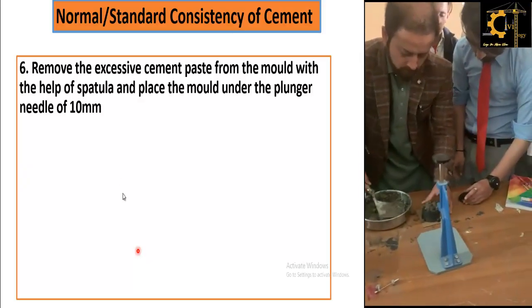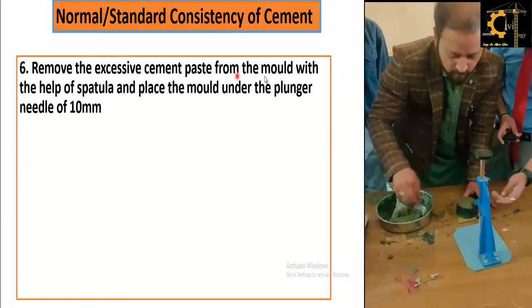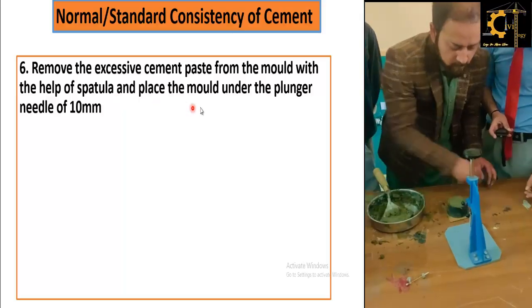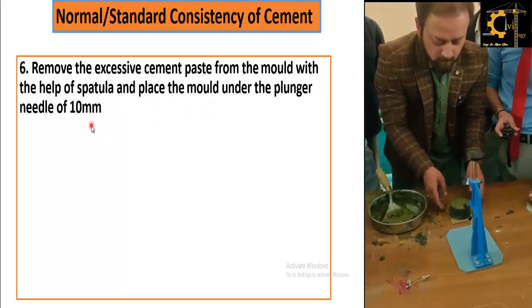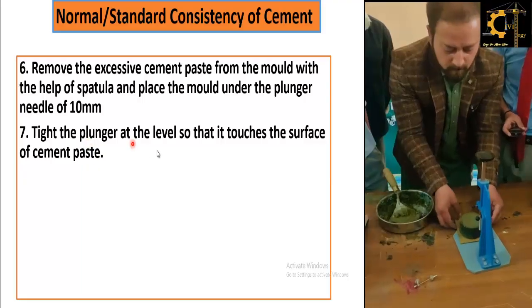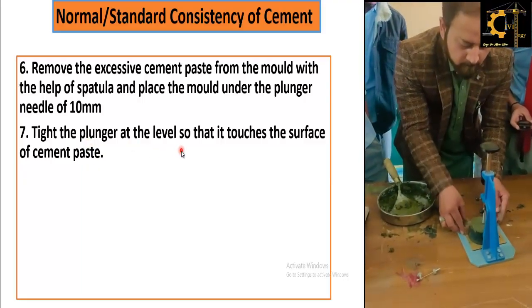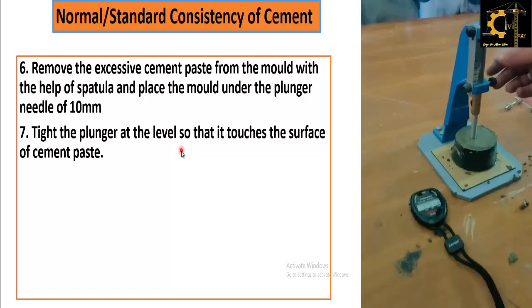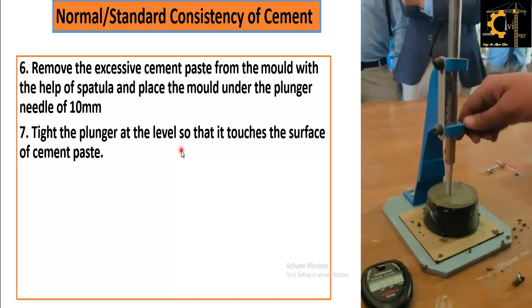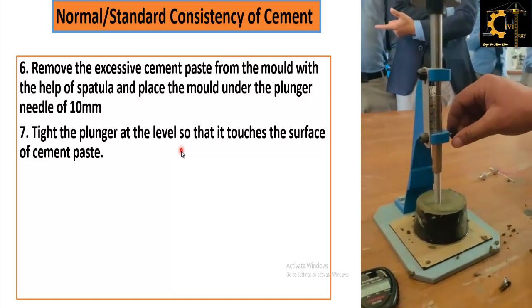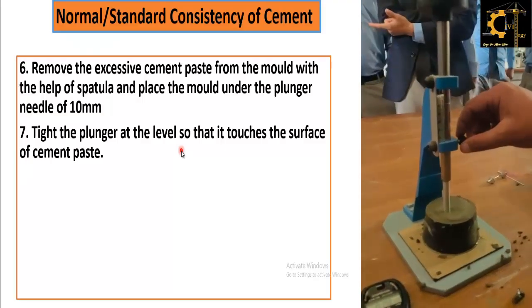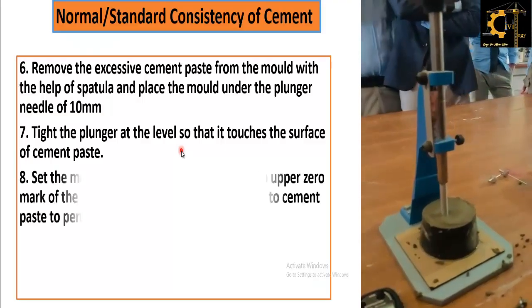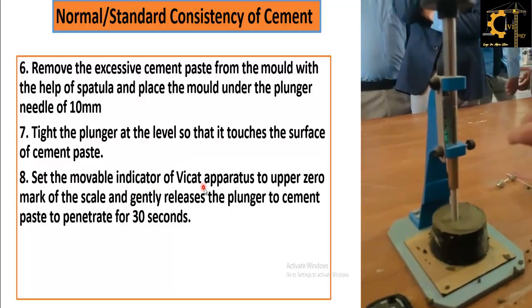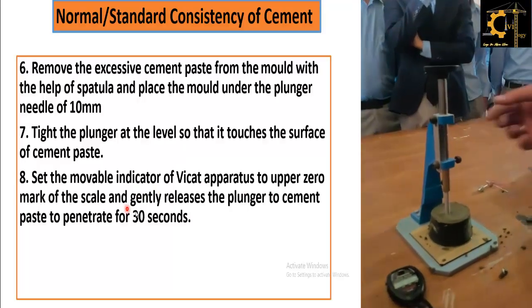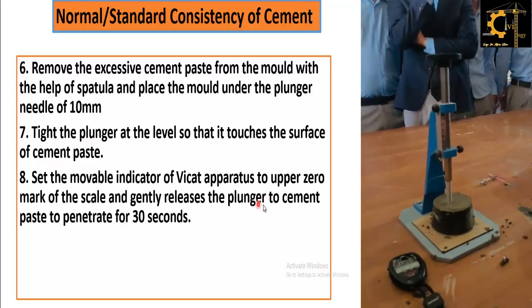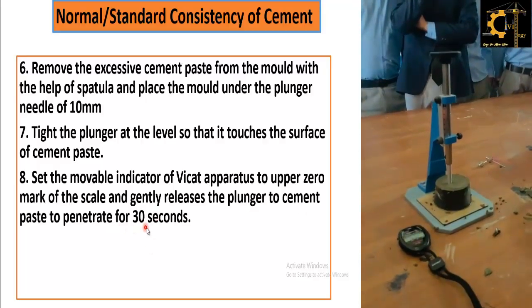The sixth step is to remove the excess cement paste from the mold with the help of a spatula and place the mold under the plunger needle of 10 millimeters. Now tighten the plunger at the level so that it touches the surface of the cement paste, and also note down the value on the graduated scale when the plunger touches the cement. Set the movable indicator of the Vicat apparatus to upper zero, mark the scale, and gently release the plunger to penetrate the cement paste for 30 seconds.